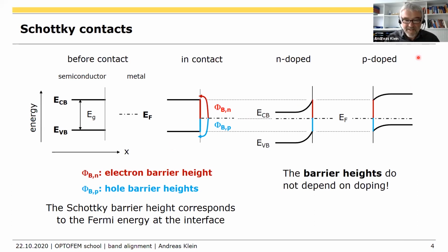That is also something one partially has to argue, because people say that if you do a different doping, you get different barrier heights, but that's not true. What is different, of course, is the band bending. If you change your doping concentration, the Fermi level in the bulk will be different, but the Fermi level at the interface, not. It should always be the same.